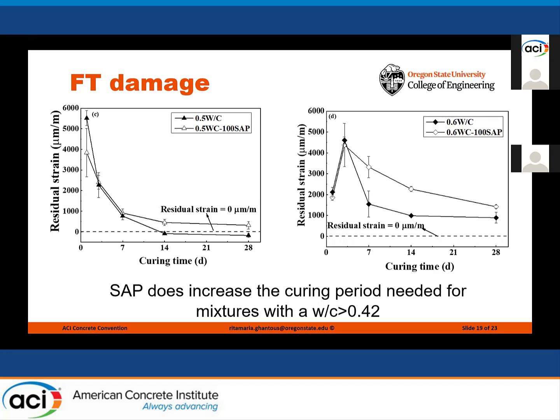And this means that SAP does increase the curing period needed for mixtures with high water to cement ratio to resist freeze-thaw damage. For example, for 0.5 water cement ratio, the sample without SAP does show negative residual strain or around 0 at 14 days of curing, while when we add SAP, the residual strain stays positive, which means freeze-thaw damage exists up to 28 days of curing. So the takeaway here is that SAP is not recommended to be used for high water to cement ratio, but it does not impact the low water to cement ratio.